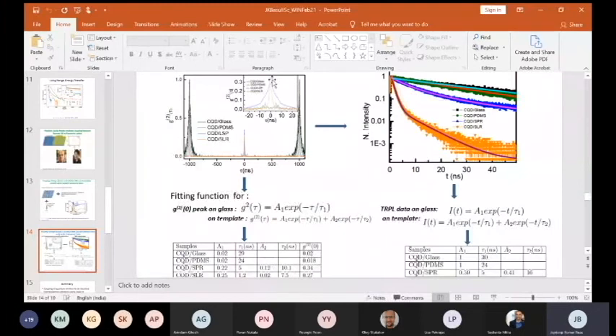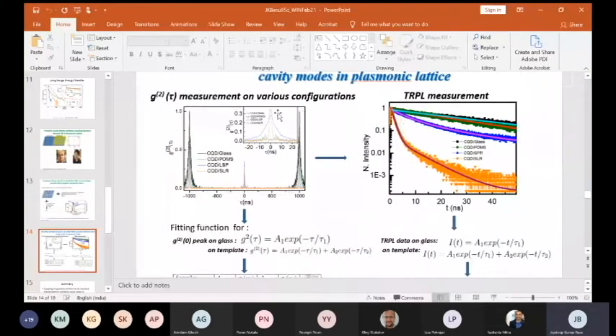This is on a reference substrate, glass, for example. If you take the same quantum dots on this template, it increases slightly, but it still remains below 0.5, which is the typical signature of anti-bunching and the presence of a single photon. What is interesting is that when you look at the lifetime, you're shining light on one quantum dot, basically. So you're looking at the photoluminescence decay from a single quantum dot. Not surprisingly, you see a single relaxation function, which typifies the lifetime, typically of the order of 20 to 24 nanoseconds. You see a weak signature of a second kind of lifetime appearing.